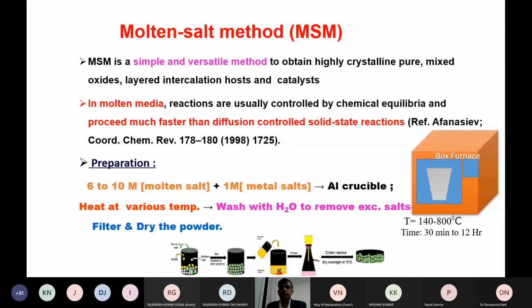Now I'm going to talk about one example in the case of oxides. One method is called the molten salt method. Compared to the solid state method, which is high temperature simple mixing of the oxides, the disadvantage is that due to unreactivity we sometimes don't get the desired phases, or we get impurities, or we need multiple heating and grinding steps. The molten salt method is one approach. You can prepare materials in crystalline pure forms or mixed layered oxides, or sometimes catalytic materials. Usually, molten medium reactions are controlled by chemical equilibrium and are much faster when compared to diffusion controlled reactions.